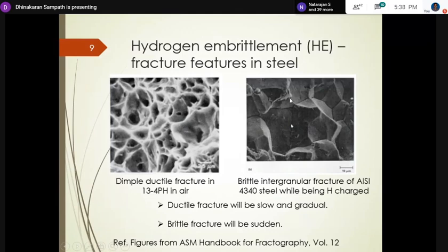And in hydrogen, the crack runs through the grain boundary, and we can see the grains themselves with facets, and you're seeing the surface of the boundaries. And this is very brittle compared to this. That means ductile fracture will be slow and gradual, but brittle fracture like this, intergranular fracture, will be very sudden. And yeah, it's without any hint.